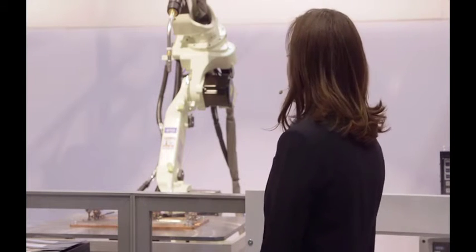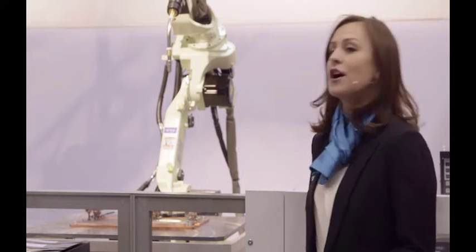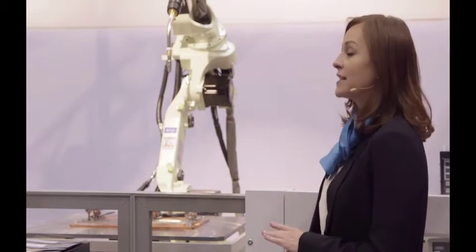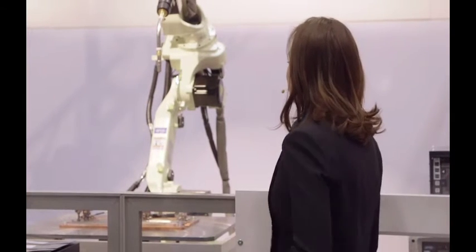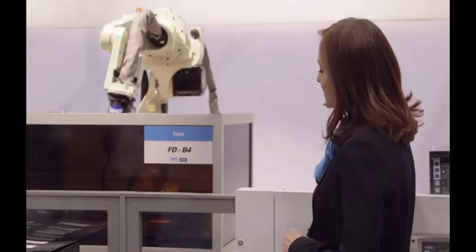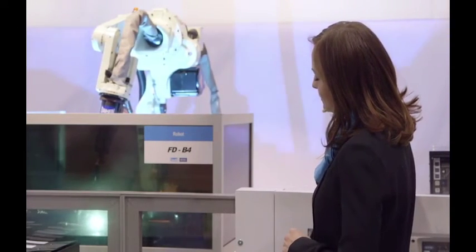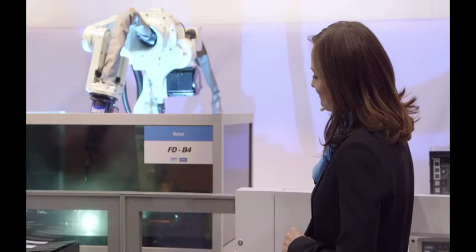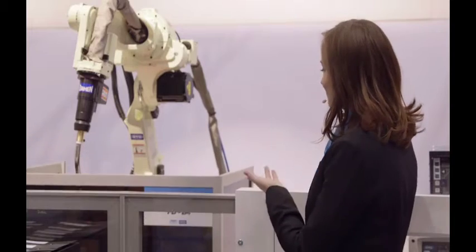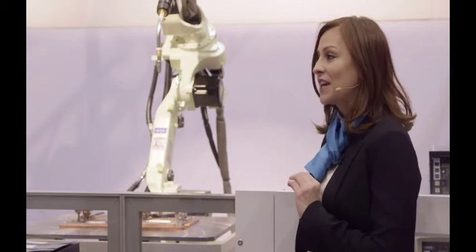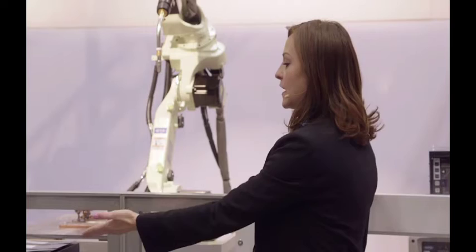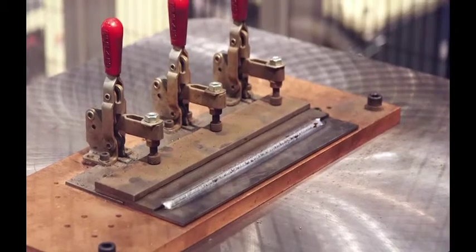Next, 3.2 millimeter thick mild steel plate used for automotive underbody parts is welded at 260 amps with a travel speed of 27 inches per minute, which is generally said to cause excessive spatter. Let's get started. Extremely low spatter welding is attainable from thin to medium plate thickness. The samples are displayed here. Please take a moment to see the high quality welding results of synchronous feed GMA welding.